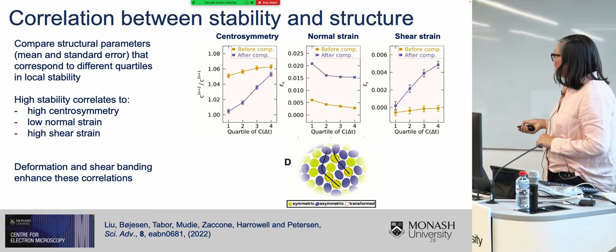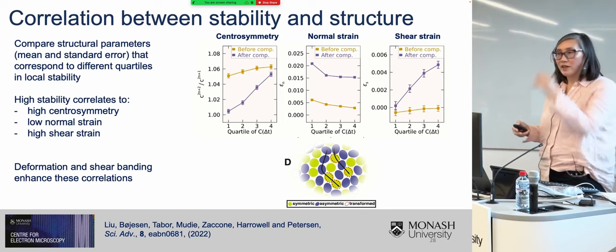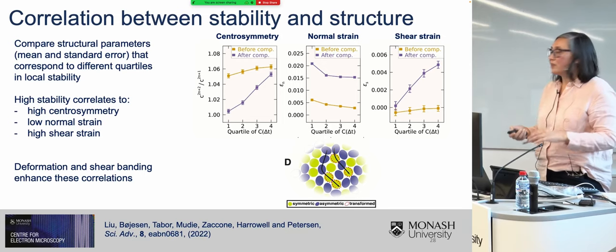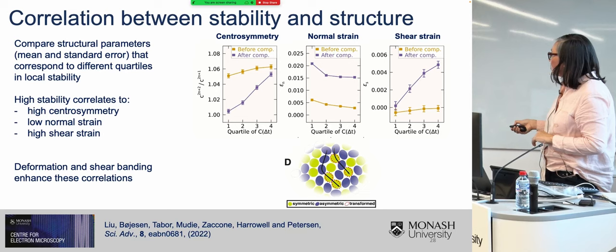So what this suggests is that inside our shear bands, we have these areas of high symmetry, these high symmetry polyhedra that were actually quenched in from the liquid, but then transform in a coordinated way to these lower symmetry structures, increasing the normal strain.